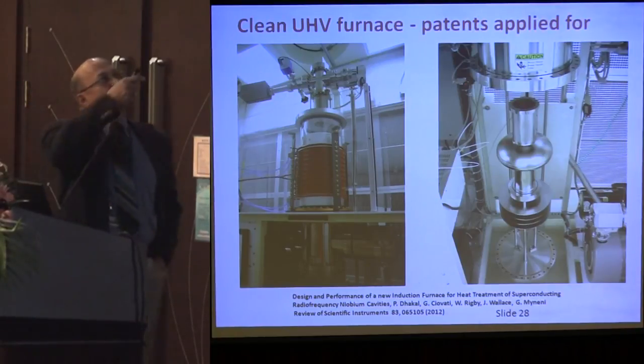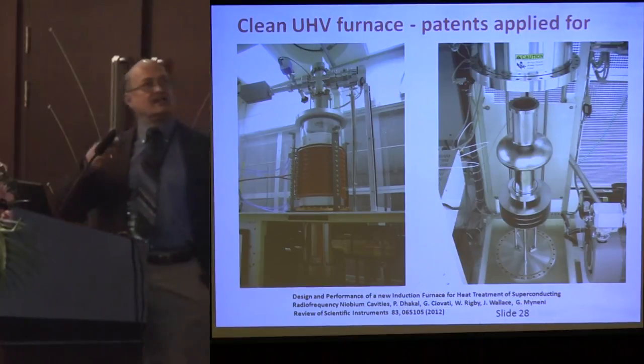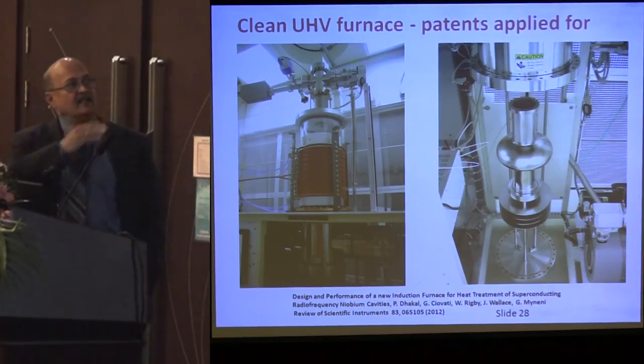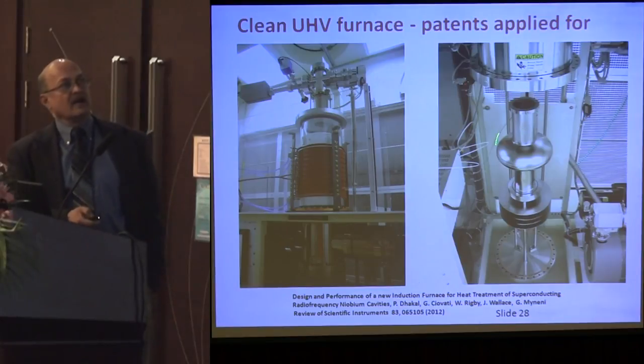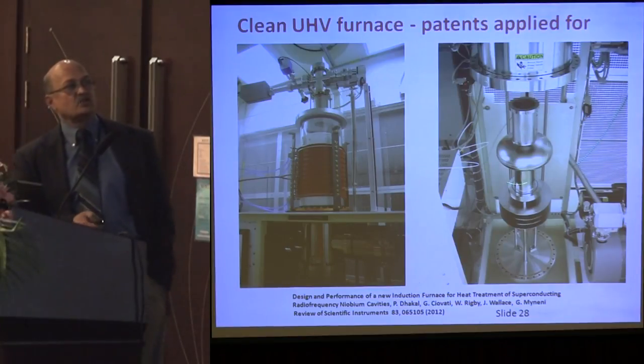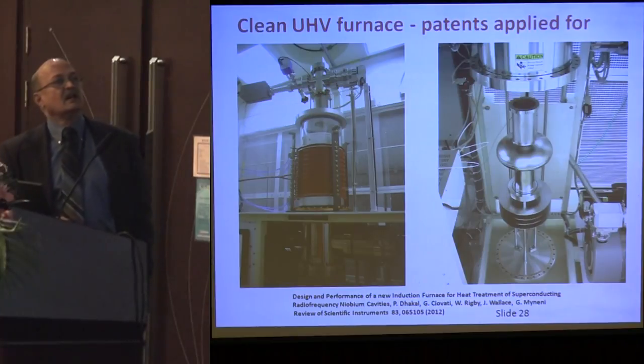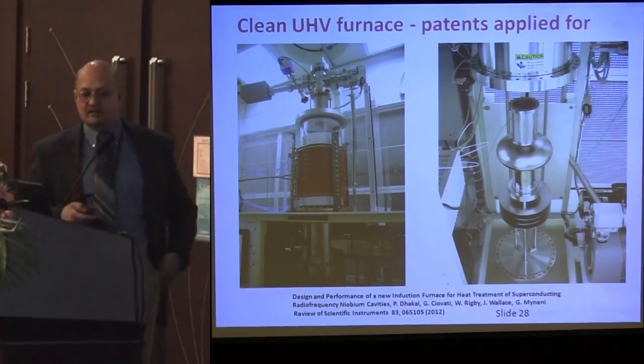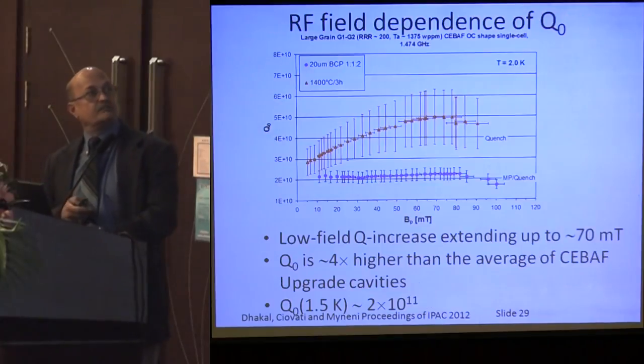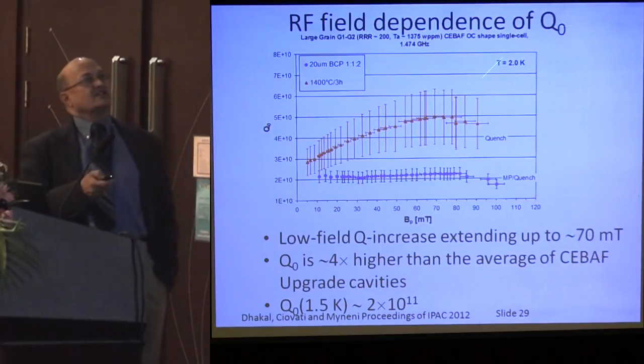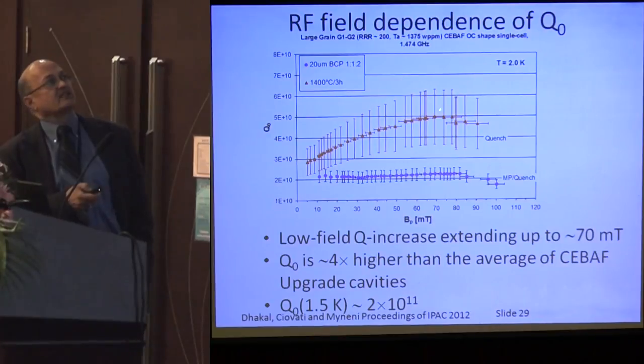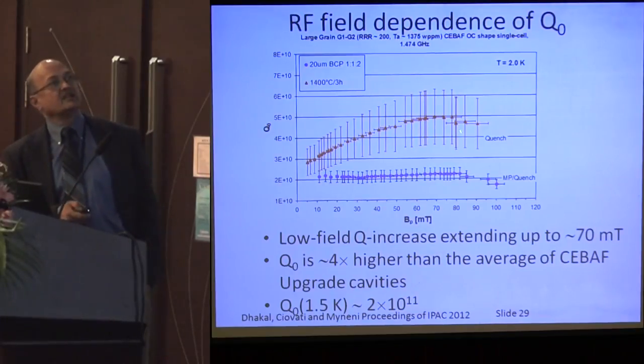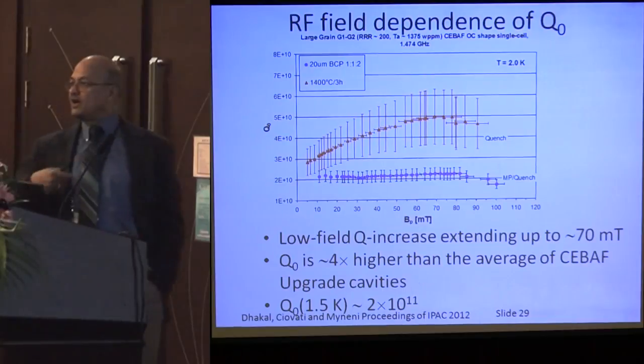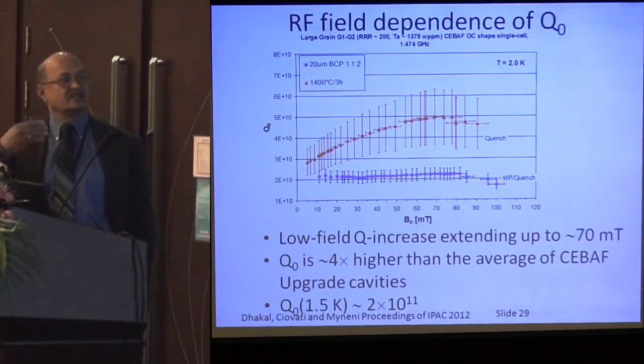Recently, we built a clean UHV furnace where we can do the final process steps in a clean way, where you don't have any surface contamination and one doesn't need to re-etch these cavities. As a result, you can eliminate the final chemistry of these cavities. With this new furnace and new process of high temperature heat treatment, we were able to get very high quality factors, something like 5×10^10 at gradients up to 20-25, which are required for the accelerator driven systems in CW mode.